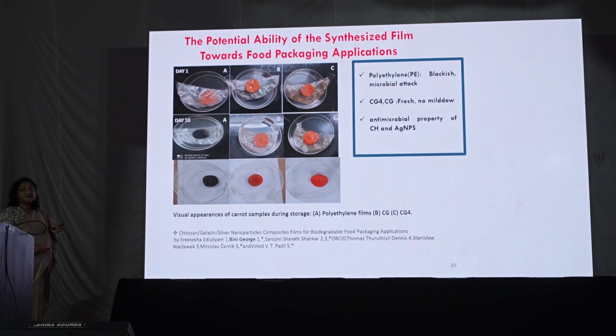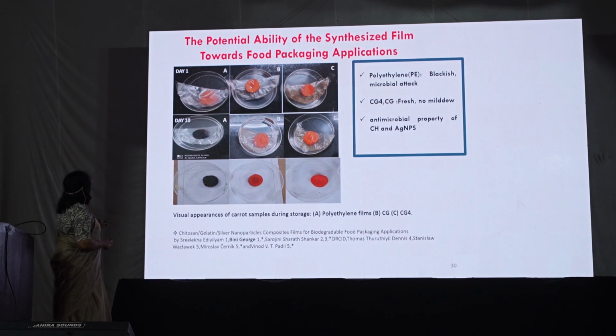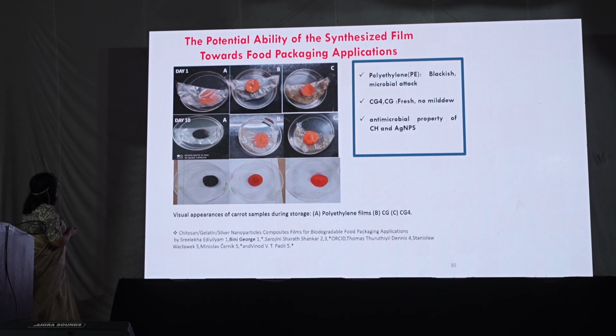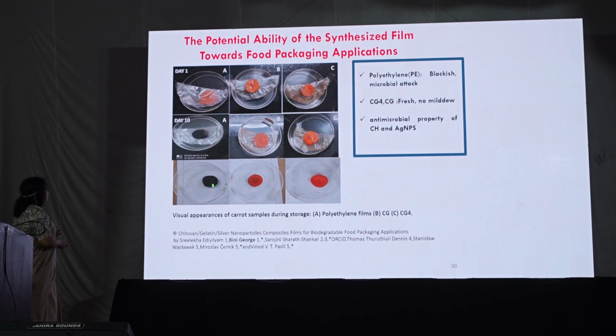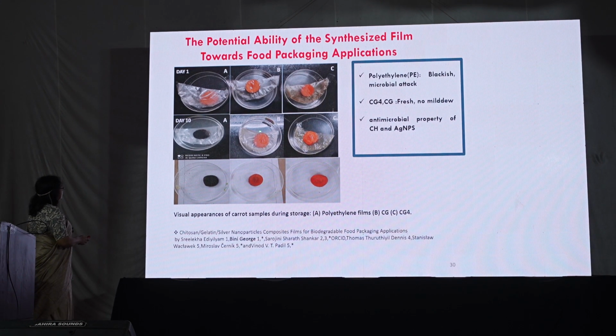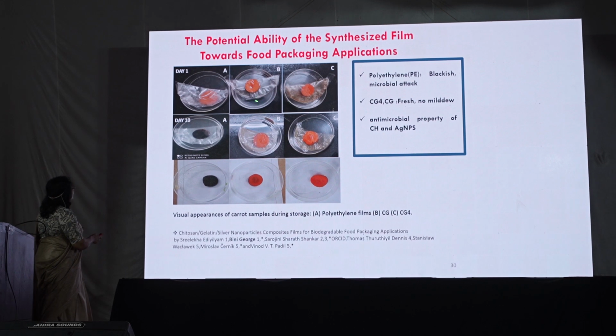And these films were used for food packaging applications, and this was kept for 10 days. Here you can see we have used the normal polyethylene film. Cut pieces of carrots were wrapped in these films, and here you can see the color change. The second one is the chitosan modified bio-nanocomposite films. Here you can see that the carrot pieces remained almost the same.